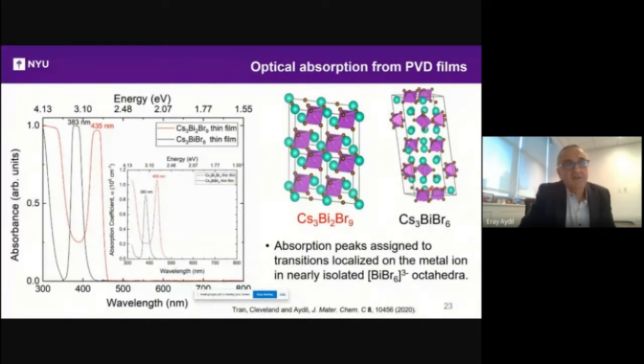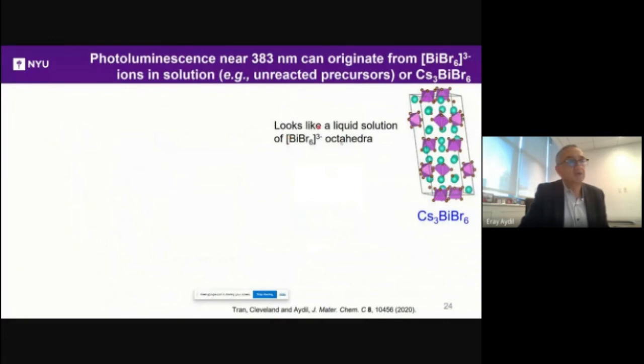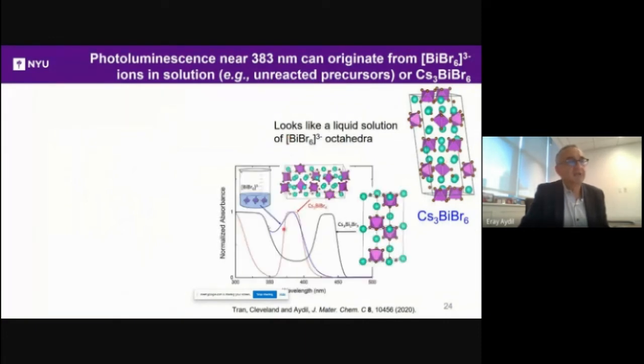And even though this is solid, note that if I were to have BiBr6 3- ions in liquid, it would look a lot like this, right? So it looks like a liquid absorption because the octahedra here are not interacting. Here, they're corner sharing, they interact, so there's a shift to 435, okay? So in fact, if I make the liquid solution, it overlaps with the solid, and I know that it's not contamination.